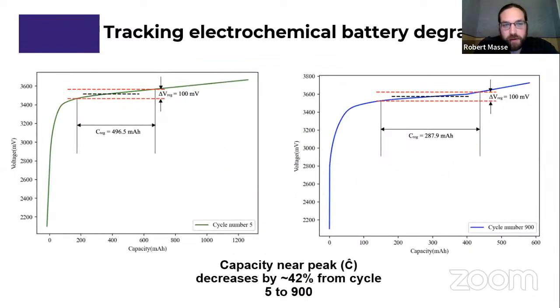The main feature of interest is that wherever that peak occurs, we take a voltage interval around that and measure the capacity around these peaks. So the idea here being cycle 5, you've got about 500 milliamp hours worth of capacity. By cycle 900, that's degraded down to less than 300. So in this case, about a 42% drop off between cycle 5 to cycle 900.